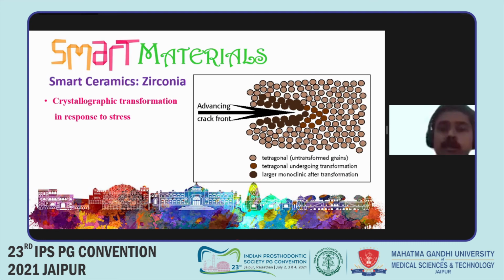And of course, lute it. When you choose your zirconia restorations and you want to think about luting it, though literature does say that you use a composite resin, remember one thing, a luting agent which is to be chosen for any restoration should be such that it should be easy to retrieve the restoration. Therefore, use a glass ionomer-based cement, or to be more clear and specific, I would choose a calcium aluminate type of cement. It's got very good bonding to the tooth structure, and at the same time also lutes zirconia restorations very well, and both of them are smart enough. So therefore, use this combination of materials together to see to it that you work as smart prosthodontists.